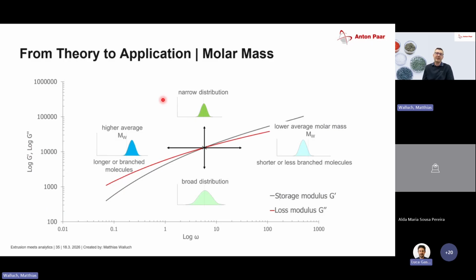So we get information if we have a higher or lower average molecular mass, or if we have a narrower or broader mass distribution. Be careful if you're comparing completely different materials. This approach is not really relevant, but if you compare similar materials, this is very nice. For example, if you do some tests on a material that is reused, so recycled, then you will see an effect that probably brings you to a lower average molecular mass and a broader distribution.